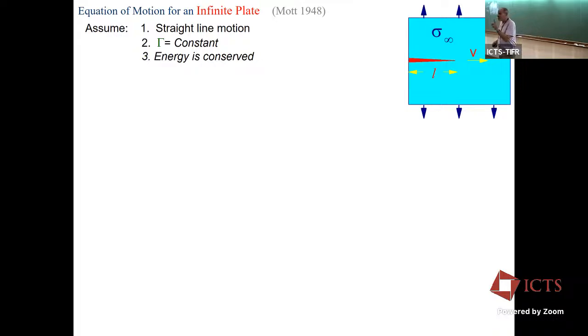We're also going to be assuming the following reasonable assumptions. Number 1 is that the crack is moving in a straight line. We're not letting the crack wiggle or do anything fancy. Single crack, moving straight ahead. The energy to break, the fracture energy, the energy to break a unit area of bonds here is considered to be constant, not dependent on the velocity or anything else, which is generally fine. And we're also assuming that energy is conserved in the system. That's all we need. Now let's use that to develop an equation of motion.